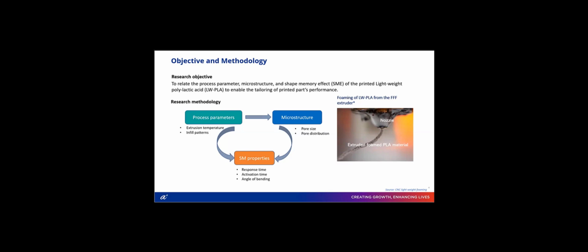So now, what is this foaming lightweight PLA? The foaming additives are added into the PLA. At higher extrusion temperature, the foaming additives are activated, through which the microstructure of the PLA is controlled or altered, and the density and overall weight of the structure are altered.